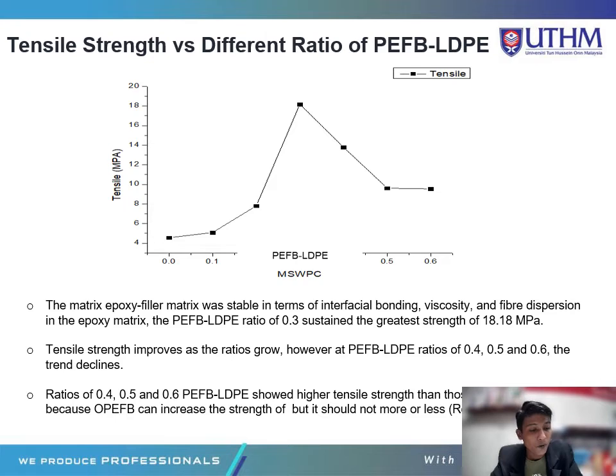Ratios 0.4, 0.5, and 0.6 of PEFB show higher tensile strength than the 0.1 and 0.2 ratios, because PEFB can increase the strength, but it should not be too much or too little, according to the Rosland study 2018.